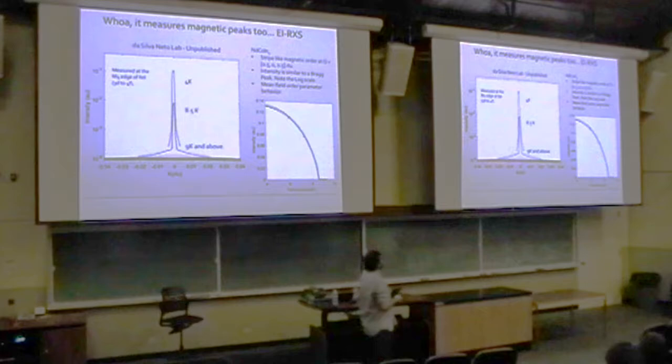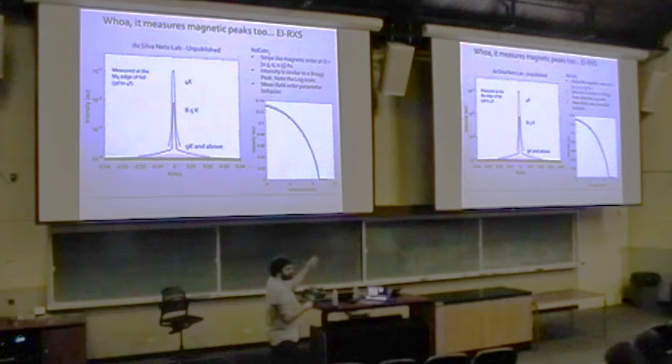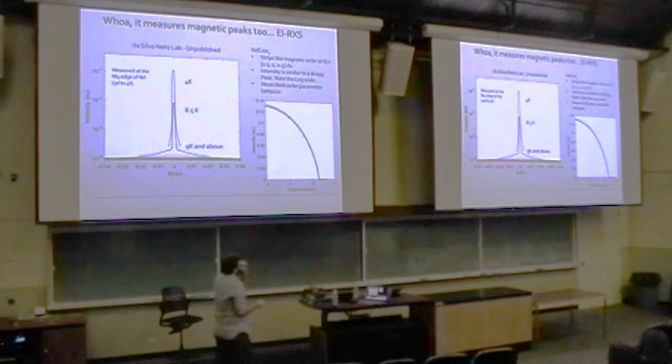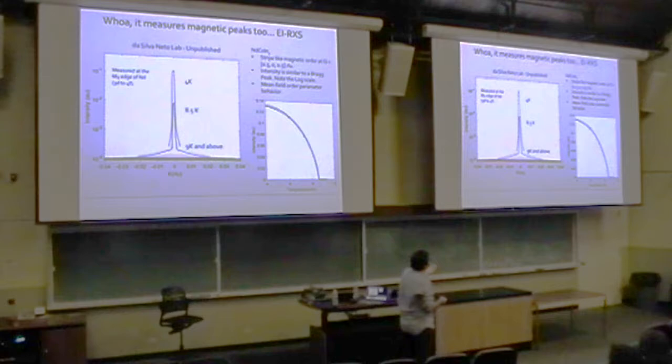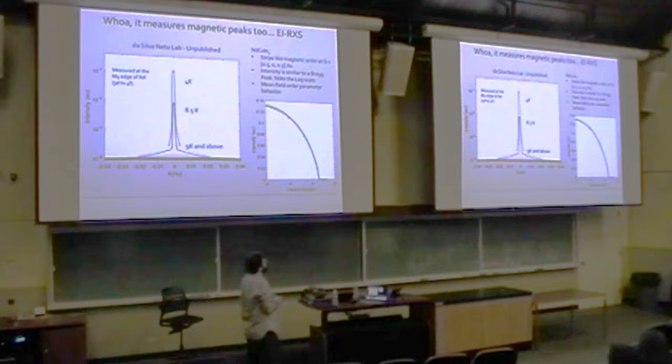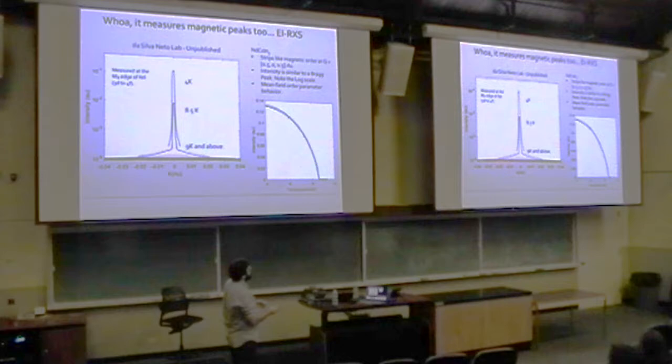Right? So here I'm on a log scale, okay, and this thing orders in a magnetic structure that's stripe-like with a wave vector in reciprocal space at 0.5, 0, 0.5. Okay, so only one direction or the other. And if you go below the transition temperature, the Néel temperature here is 8.5 Kelvin or so. If you go really low, 4 Kelvin, you can see that the peak is very large, very sharp, and close to the intensity you expect from a Bragg peak also. And it shows a beautiful mean field like order parameter.